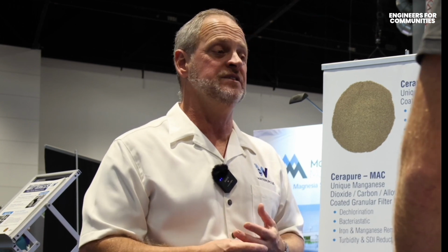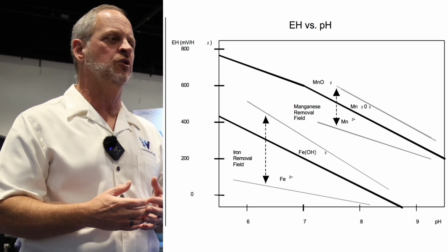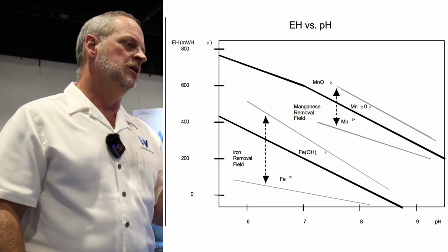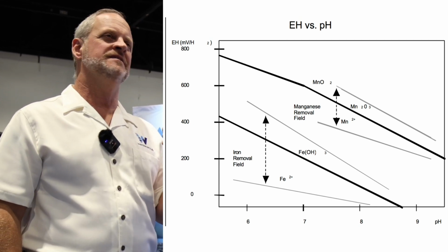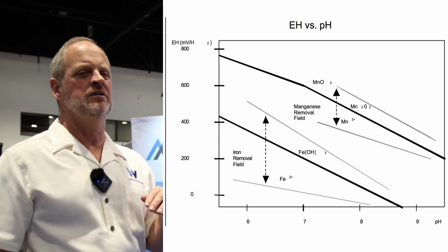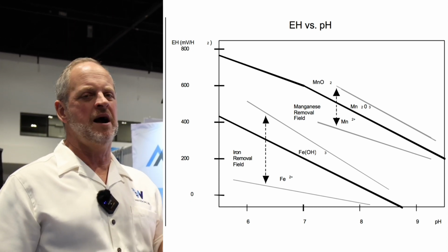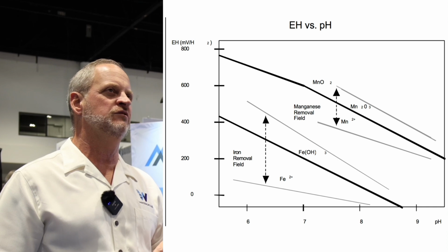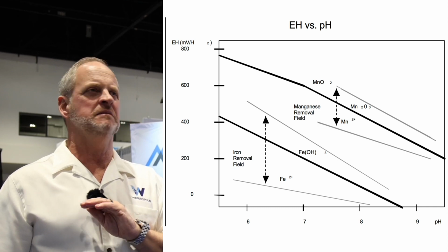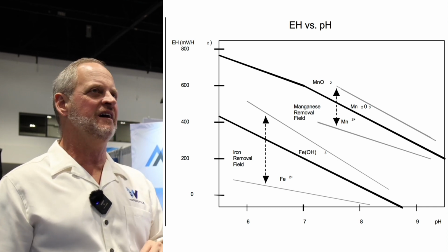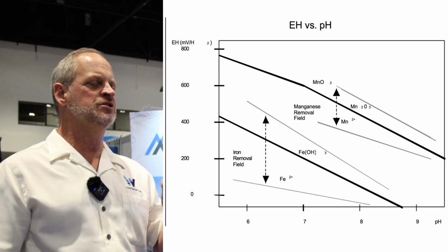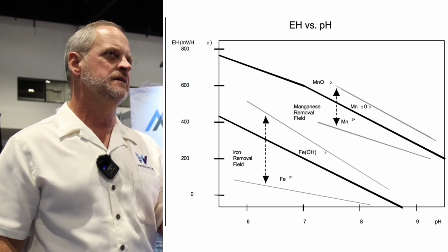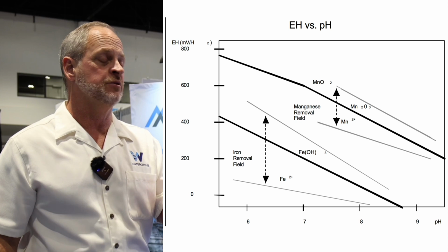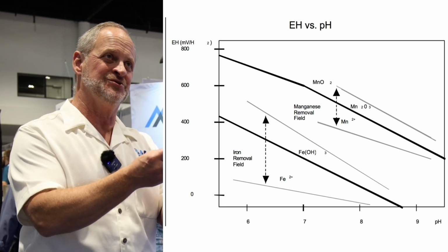And it is very much influenced. pH is a huge one. Oxidation potential is really important. A lot of people want to treat manganese like iron, and they're just different. You can get iron at a fairly neutral pH with a mild amount of oxidant and get pretty good removal. There are times you won't even budge manganese. It's much more stubborn to convert to that precipitated component. Some people use permanganate as a way to catalyze that crystal structure.